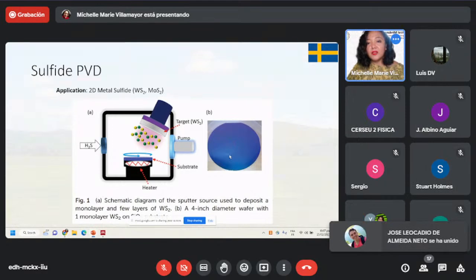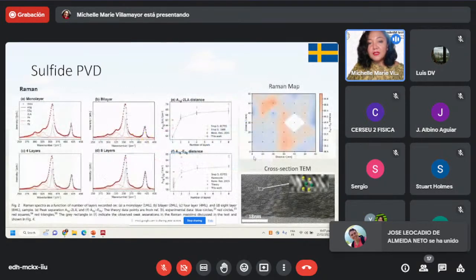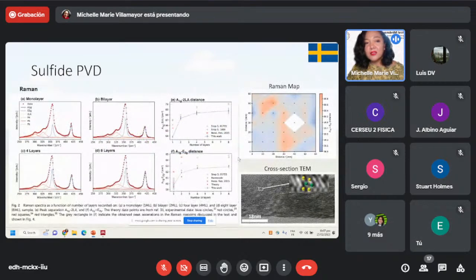Now, we tested how many layers of tungsten disulfide were on our sample, and we used Raman to do that, because for Raman, there are signature peaks, and if the separation is at certain distances, then we know that this is 1 layer or 2 layers or 4 layers of tungsten disulfide. And we have tested the monolayer, bilayer, 4 layers, and 8 layers. And in summary, we have all of these results here.